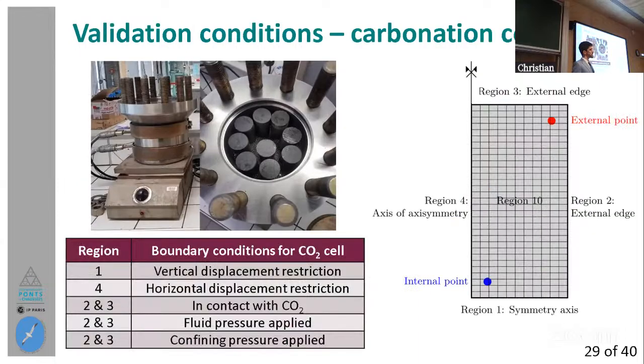So first here, what we have is the carbonation cell. This is the geometry that I have adopted. In general terms, it's a rectangle with an axis of symmetry here, and then another axis of symmetry down here. And regions 2 and 3 indicated there represent the external edge of these cylindrical specimens. I have applied the conditions corresponding to the carbonation cell, which are CO2 concentration in regions 2 and 3, confining pressure and fluid pressure in these two regions.